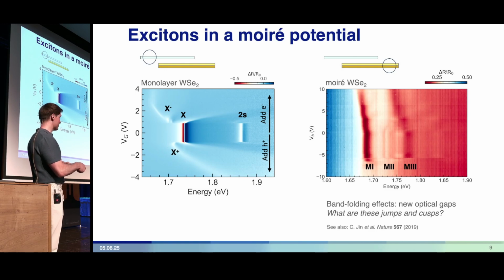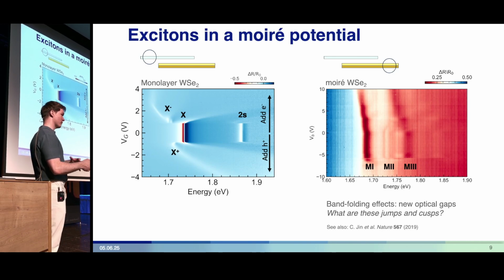While the electrons that we're injecting at these cusps are residing in the WS2 layer. Nevertheless, because it's a heterobilayer, the layers are hybridized, so some amount of this exciton is actually coming from the WS2 orbitals. So there's a screening effect, which gives us, I'm not sure if you can see, but at the cusps there's an increase in oscillator strength.